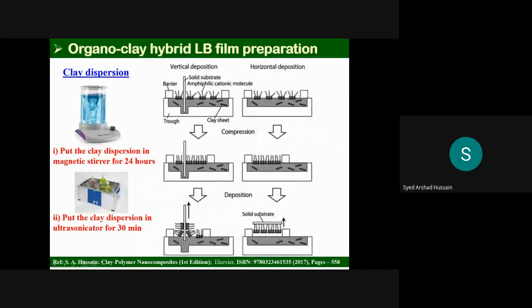So, how do we prepare this organoclay system using this LB technique? What we do, first we prepare a clay dispersion using this magnetic stirrer for 24 hours. Then we put this dispersion on an ultrasonicator. Then we put this dispersion in the trough of the LB instrument, and we spread some cationic amphiphile on the surface.